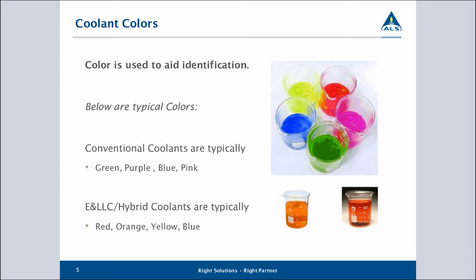Something else that can be done with the dye is that there are some coolants where you get a color change that can be triggered by the dosage rate. So you can get a sense of whether your additives and your water are in the correct ratio based on the color. There's a color change if there's too much water or not enough water in the coolant. Some coolants will also contain a phosphorescent dye that makes it easier to identify coolant leaks. If coolant is leaking out of a system, the coolant may boil away, but it'll leave some of the dye behind, and this can be spotted using a dark light, that type of thing.